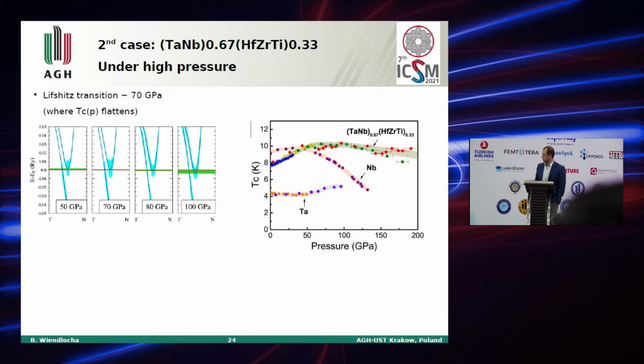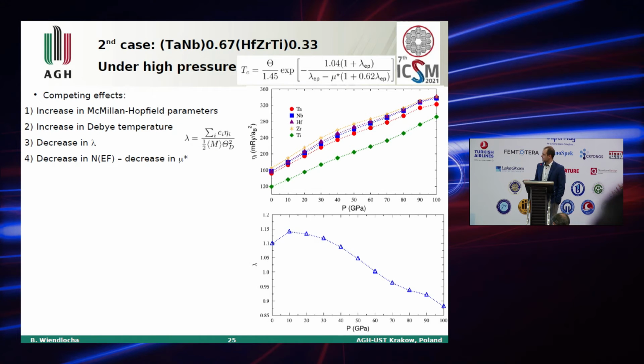So this may be related to this fact. And as far as the electron-phonon coupling and critical temperature is concerned, we found several competing effects. So Mc­Millan-Hopfield parameters increase with pressure, but also the Debye temperature increases. That was simulated using the Grüneisen parameter measured through the thermal expansion in this work. So the McMillan-Hopfield parameter increases, but the Debye temperature also increases, so at the end of the day lambda decreases. So the lambda smoothly decreases with pressure.